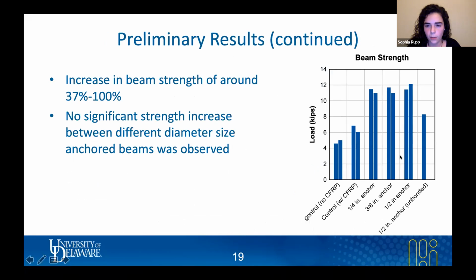This is a little bit of a better representation of all the beams that we tested and the strength that was reported for those beams. We found that there was around a 37% to 100% increase between the anchored beam to the unanchored beam.